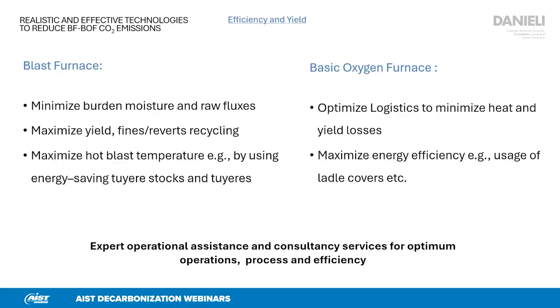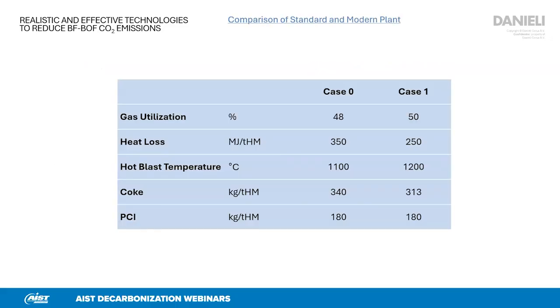And when we look into the basic oxygen furnace, we have come to realize that many steelmaking companies could optimize their logistics to minimize the heat and the yield losses, and also to maximize the energy efficiency, for example, by usage of ladle covers. And if the best available technologies and some efficiency and yield improvements are being factored in, then emissions will be reduced already by some 5%, as a result of improving the gas utilization, reducing heat loss in the blast furnace, and increasing the hot blast temperature.